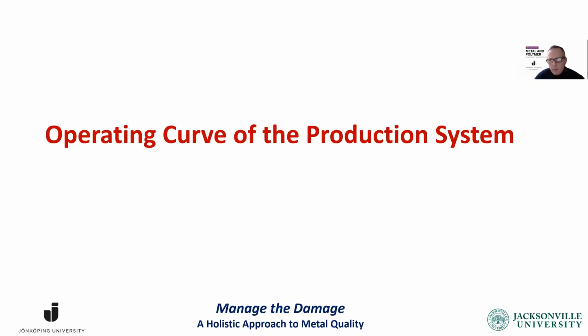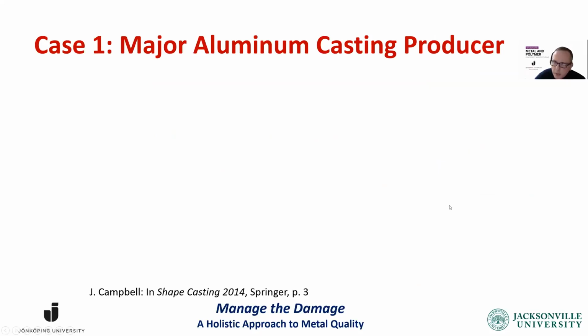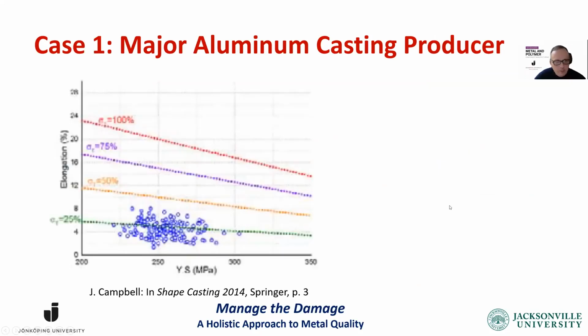So that perhaps in the end, when we collect all this data, we can develop what I call the operating curve of the production system. And what do I mean by that? I'm going to give you 3 examples. One was reported by Professor Campbell. He reported these results came from a foundry where they looked at the results. No matter what they did, the quality index fluctuated between about 5% to 30%. And there was a lot of scatter, but even the best efforts produced about 0.25.